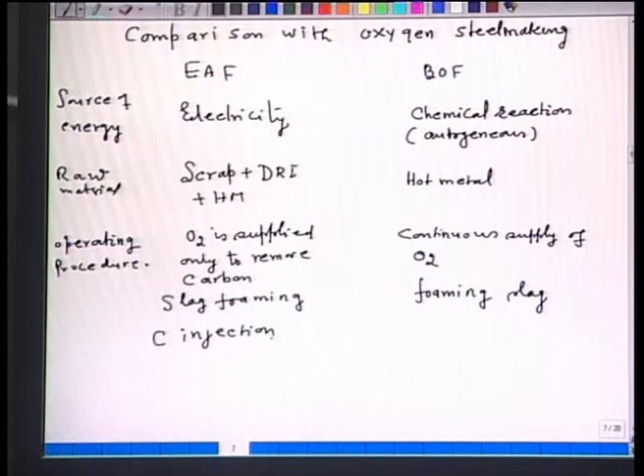Carbon injection is purposely done in order to create foaming. How is it done? For foaming, one requires a gas forming reaction, that is C plus O equals CO. In an electric arc furnace operating with 100% scrap, hardly any carbon is present which will give you carbon monoxide gas. So, for submergence of the arc in the foam, extra carbon is injected, oxygen is also injected, so that carbon monoxide evolves and the slag foams.